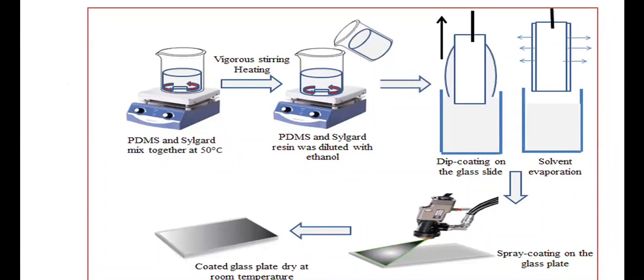In ours, we use a very simple synthesis method where our raw materials are PDMS and Sylgard. We mix them together at 50 degrees Celsius. The PDMS and Sylgard resin was diluted with ethanol, and we stir it using a normal stirrer without any heating effect. There is no heating. After that, we do a dip coating on the glass slide, or we can do a spray coating method. Dip coating is for small glass substrates like glass slides, or for large glass plates, we use the spray coating method, and we leave it to dry at room temperature. It dries within 10 to 15 minutes at ambient condition.